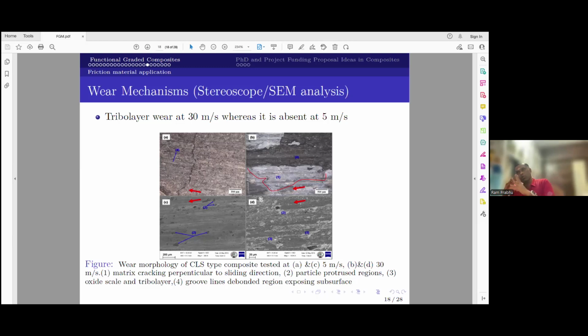When I go to the higher sliding speed, temperature is very high, oxidation is happening, so a good amount of tribo layer is also formed, delamination starts coming up, and oxidation wear starts coming up. So at low sliding speed it is abrasive, and at high sliding speed you typically have oxidation and delamination wear dominating in both the functional as well as your traditional composites. But the intensity of this wear,